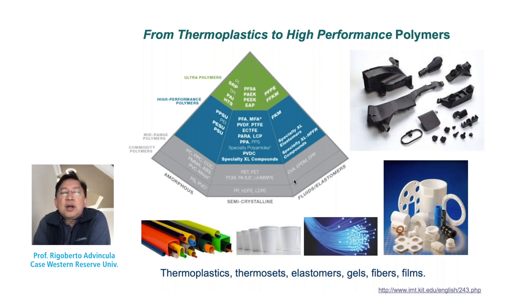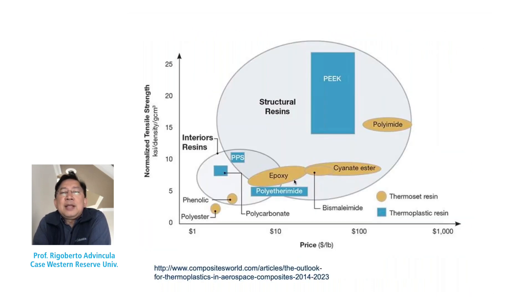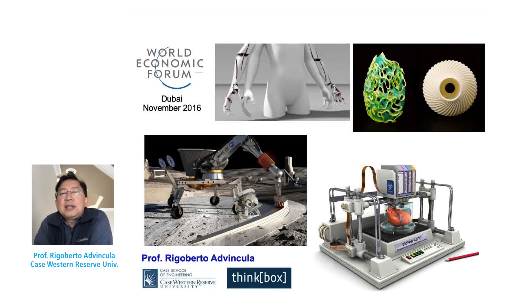When we talk about polymers like PEEK, PEI, Ultem, PBI, PESU — these polymers have not only very good resistance to chemical environments and high melting points, but also very good low coefficient of thermal expansion. They can even be as good as metal replacements. The value chain for high-performance polymers is that they can have very high tensile strength and properties, though their cost can be quite high. High-performance thermosets like polyimide or other cross-linking materials can rival PEEK in some ways. The bottom line is high-performance polymers are not cheap and not easy to fabricate.